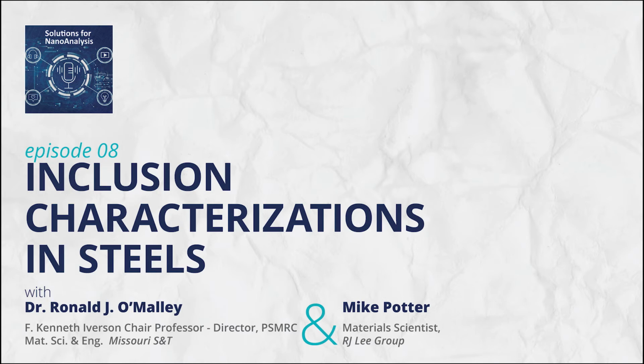For example, we've developed specialized samplers that we can take steel that is essentially representative of the steel tapped out of the electric furnace with very high oxygen contents, and then we can do deoxidation here in the lab of those simulated melts under environments that allow us to do sampling and capture of the inclusion evolution development from 1 second after deoxidation up to 20 minutes after deoxidation. So we can sample at resolutions that are really difficult to do in the plant world, but do them here in the lab. And that's actually told us a lot about what controls the evolution of inclusions and the inclusion morphology.